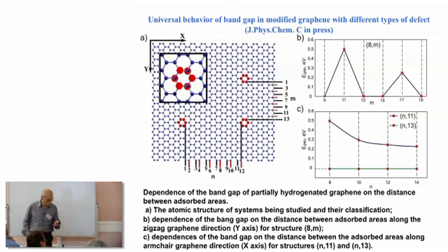And we decided to check this, to check the nanomesh materials and compare nanomesh properties with graphene which has different types of defects. Looks like here, you can see adsorbed hydrogen atoms, and when we have a periodical structure, looks like here, with sp3 carbon atoms in this area, you can see we observed behavior like here.